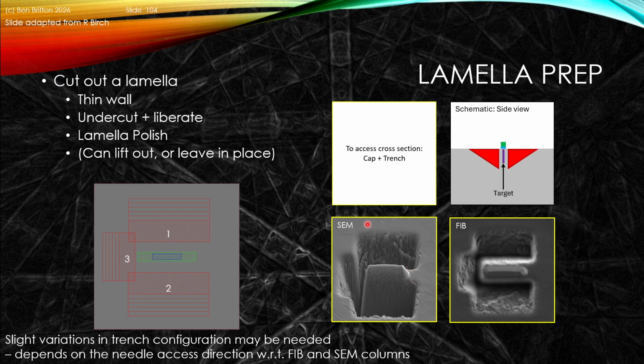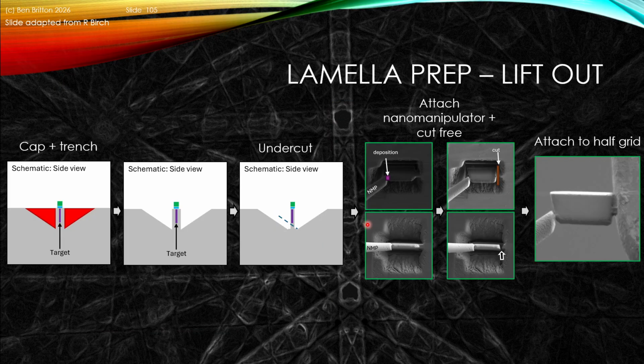We'll bring it off the surface and then weld it. So we can see this process where we've now done the trenching either side and we've capped it. We've then polished away that free surface either side, and then we do the undercut process to enable this to be a freestanding lamella. We then can take our nano manipulator and perform a small bit of deposition to weld the end of our manipulator needle onto the end of this. And then it's been undercut, and then we can cut off the lamella.